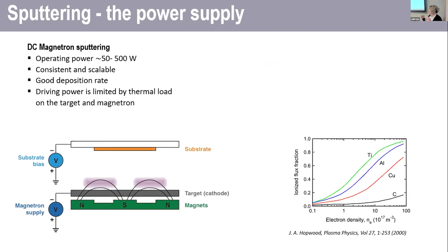When you apply a voltage to that target, you strike plasma, the magnets act to trap the plasma very close to the target, making it very dense. And that's the ideal situation for controlling your film growth.